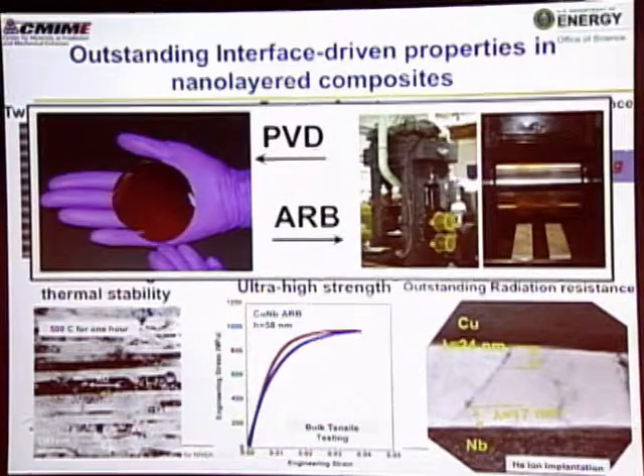So what we're going to do today is look at the difference between the materials that we can make by this type of synthesis technique compared to what we make by cumulative roll bonding, which is made in a rolling mill that looks like this. So you can see these big rolls that we have. There's actually one down below this table too. This is about 18 inches in diameter, and we feed our strip of material into here and essentially crush it